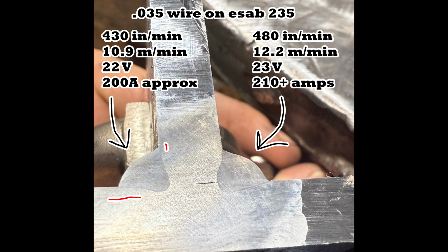The big issue I have with what's going on here is the unreliability. And what I mean is, yeah, this cut and etch looks okay on the right, and I think those settings would be acceptable to weld 3/8 steel. But again, this is a flat position. Who knows what it would do in overhead? Who knows what it would do on mill scale or dirty material and used material, like in the repair world, say on some excavator or something. The results are just unpredictable. And this cut and etch, you know, who knows what it is near the start. It could be significantly worse, like on the left side weld, than what we see here.